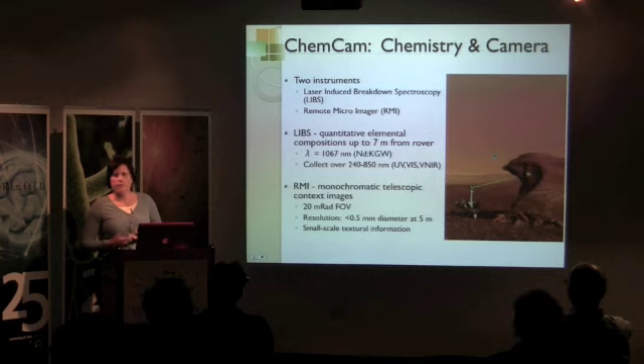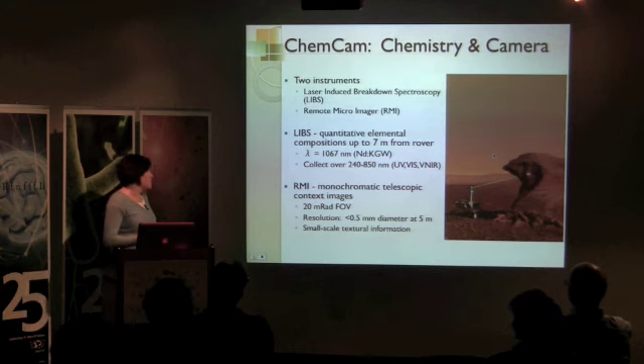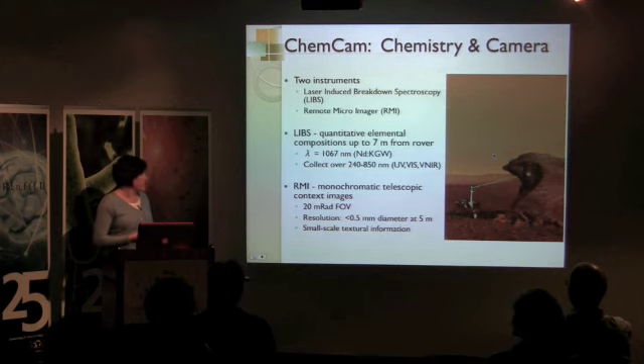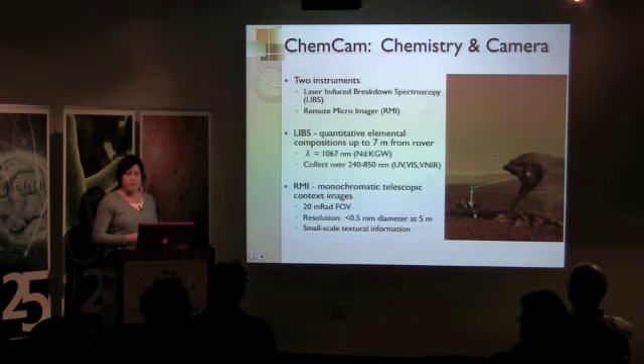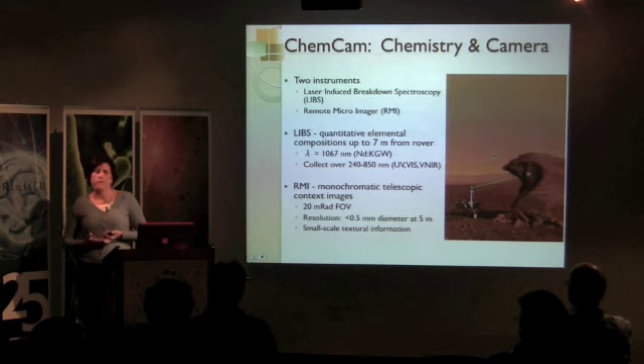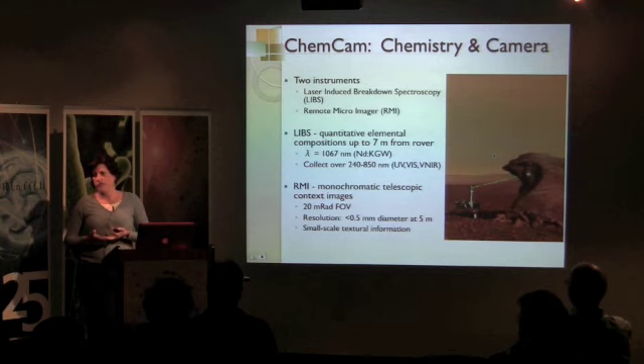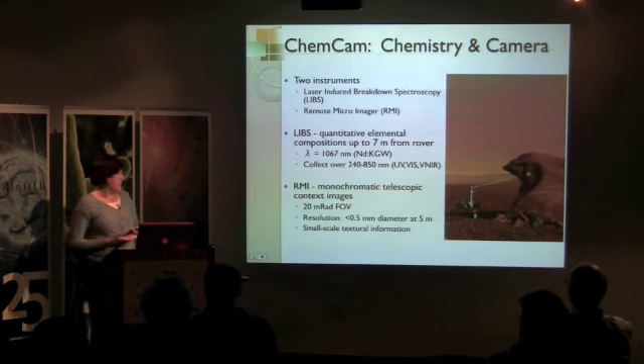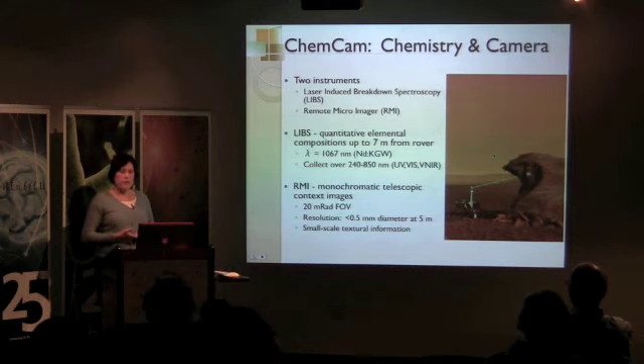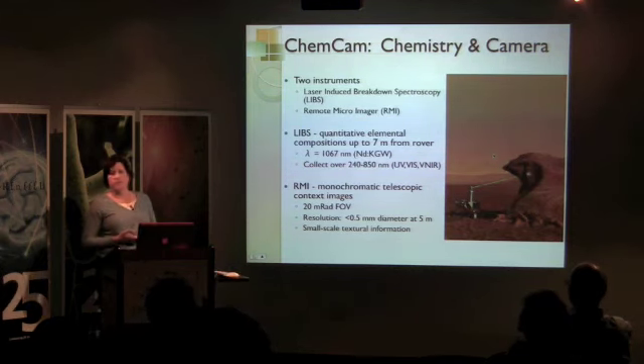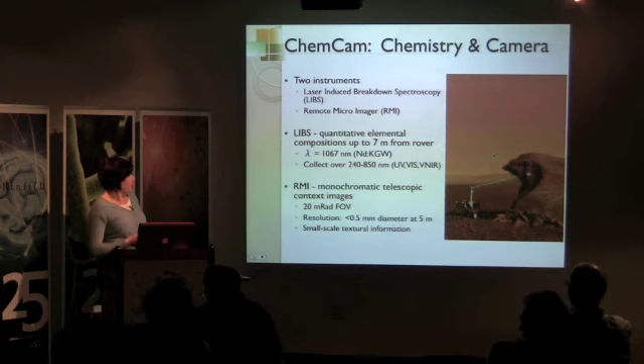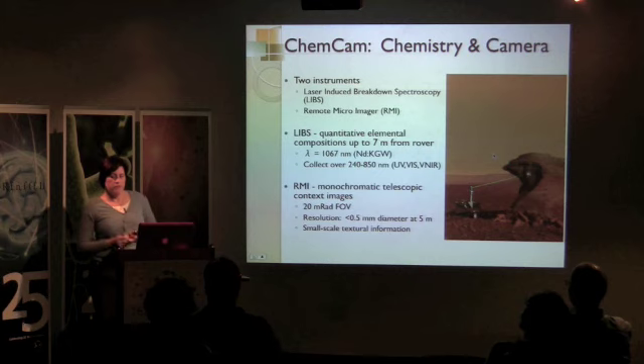So we say that we expect standoff capabilities of up to 7 meters from the rover, and this LIBS uses a special, or rather unusual, kind of laser at 1067 nanometers. This is a neodymium-doped potassium gadolinium tungstate. So it's very similar in frequency to a neodymium YAG laser, but it has much higher lasing efficiency at the low temperatures and low power requirements that ChemCam will be working with. It's going to allow us to collect over a large spectral range that encompasses UV, Vis, and the near IR, and that way we'll be able to see a large spectral range of our sample materials.